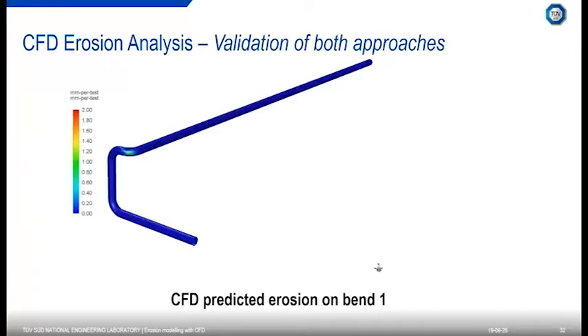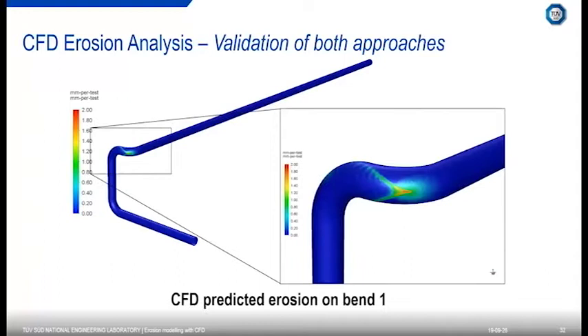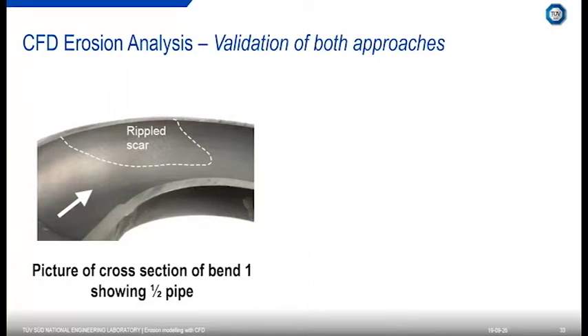So we can get our prediction on bend one. You can see the actual highest erosion rate, in millimeters per test, is around 1.8 to 2 millimeters at that particular location, right in the center of the pipe. So the question I have is, is that realistic? We can take our measurements from this configuration.